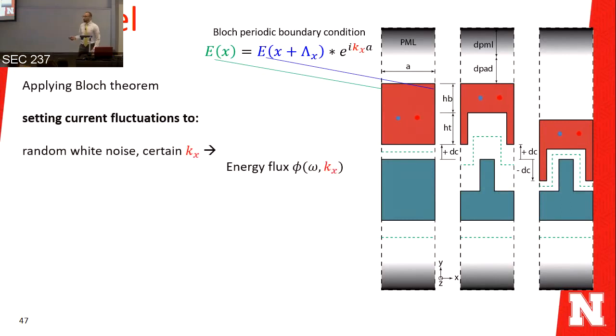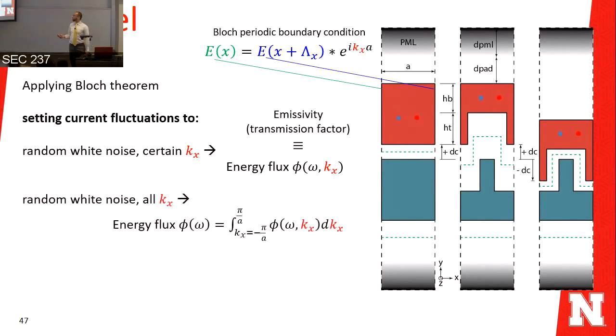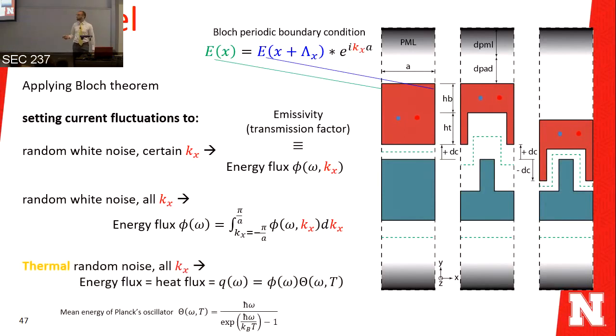So in our simulation, we have applied a random current source with white noise and a certain wave vector. We have achieved this energy flux, and this is very similar to the emissivity or the transmission factor between the two structures. If you integrate along all the possible values of kx, you get this energy flux. If you need to calculate the actual heat flux, you need to multiply this energy flux by the mean energy of Planck's oscillator. Then you will get the thermal radiation out of this system.